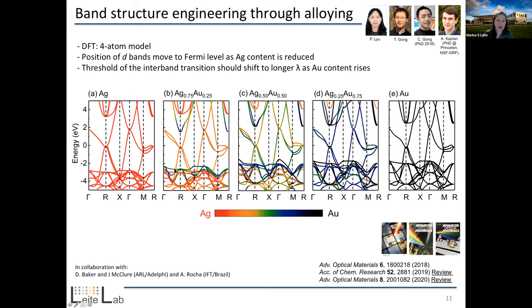Now, besides that, you can see a break in degeneracy, as expected, in several of these electronic states, because now we have different elements constituting the unit cell. And third of all, which might be one of my favorite features, is that Alexandre was able to actually quantify the contribution of each one of the metals to the electronic structure. And the reason why this is so important is that, for example, if you now look at the 50% silver and gold alloy, we do see that, for instance, at the gamma point, it is actually dominated by the gold contribution, meaning this darker color here. So the color scale has actually a meaning here, okay? It's not only to make it look pretty. So this became a very useful tool for us to correlate these measurements with the optical measurements.